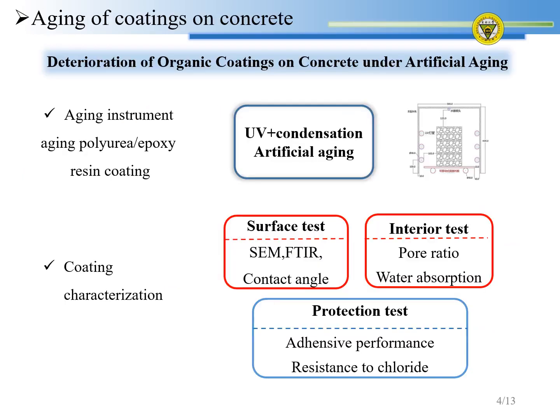In order to age the coatings on large-scale concrete samples, we made an ultraviolet aging box to continue the following study. This is because our normal concrete samples, with side lengths of 100 mm, cannot be placed in the specialized equipment used for aging coatings. After aging, 3 parts of characterization of coating are carried out, including the assessment of coating surface and the interior structures, and the protection performance.